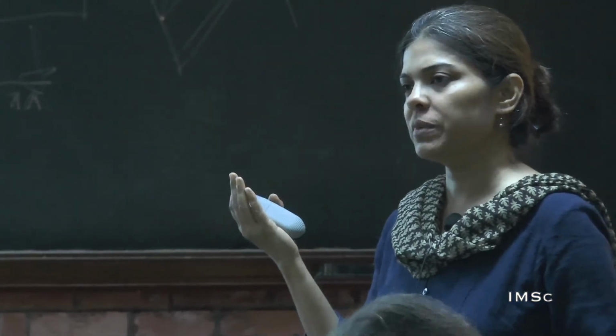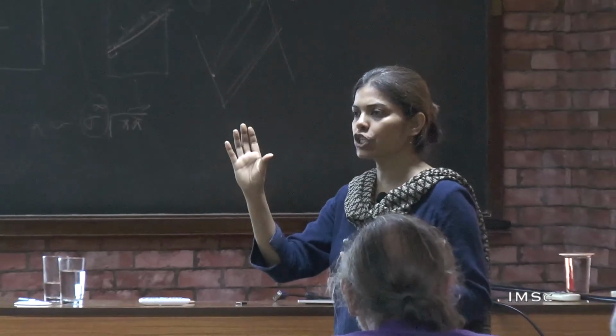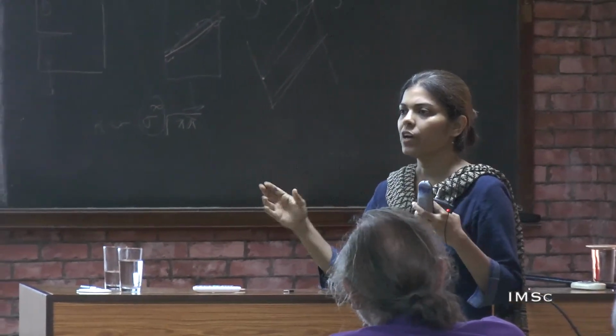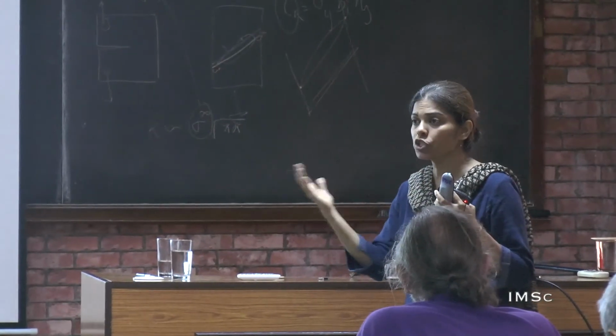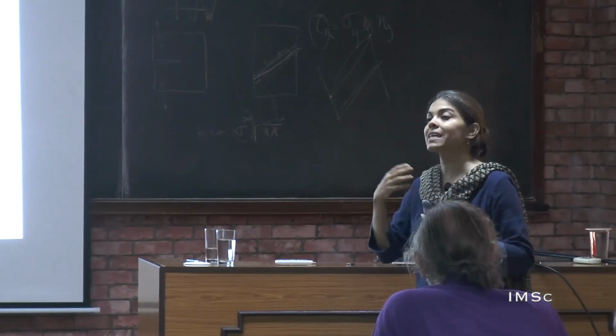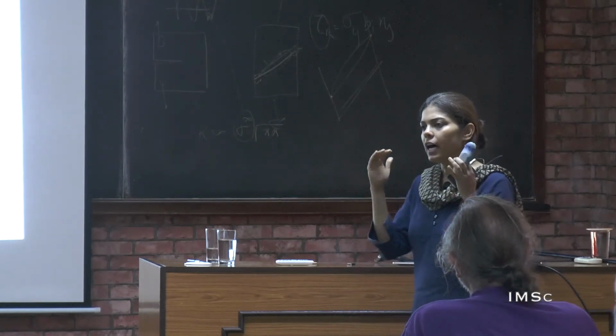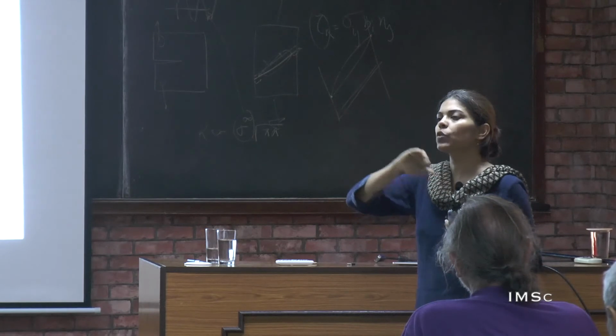In front of the notch, you mean? In front of the notch. Yeah. You have a deformation which is developing the roughness, and it does not have sufficient triaxiality there. Because of the lack of triaxiality. So that is what we are trying to argue, that this growth of a fatigue crack has been broken into stage 1 and stage 2 with clear demarcations. We feel the early stage 2 is part of stage 1. Stage 1 and early stage 2 happen simultaneously, and which precedes the other is not clear, because otherwise you would have seen a consequence of growth.